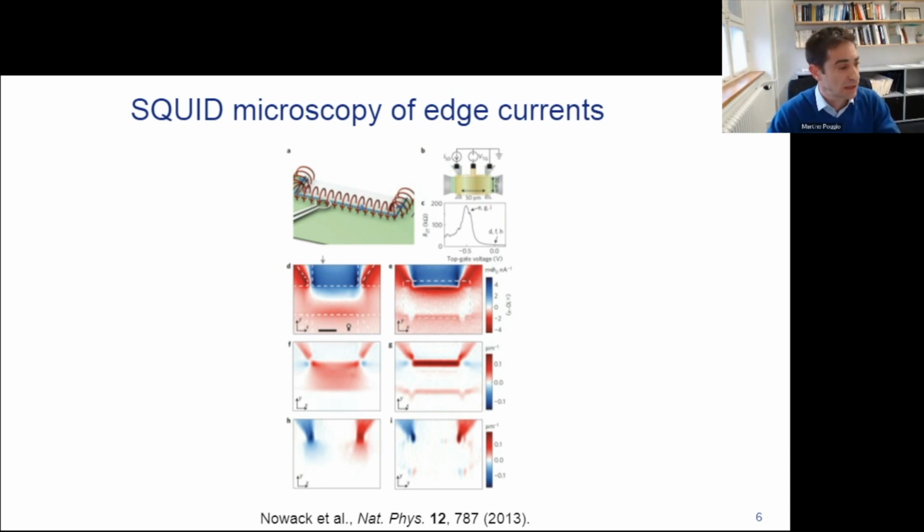On the other hand, a measurement like this one makes measurements of stray magnetic field, and from this stray magnetic field you can infer, say, what's going on with flowing currents or with magnetization underneath. These are applicable to a much wider set of phenomena. The stray fields can be produced not only by magnetization patterns but, as I said, current distributions, and the samples that you can measure can span across conductors, insulators, soft biological matter, and a whole variety of other things. So anything which produces a magnetic field. The common methods for this are what I showed in the beginning, using a fine magnetic powder as demonstrated in the 1800s and later improved by Bitter, Lorentz microscopy, electron holography, and a number of scanning probe techniques.